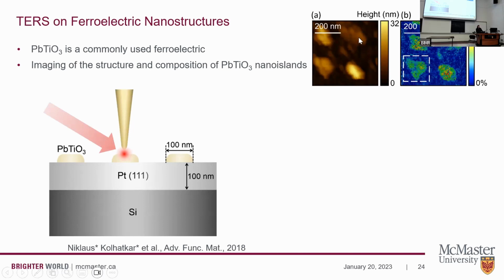So we measured simultaneously the topography, which is presented on the left, and the Raman signal, which is presented on the right. The yellow regions correspond to the lead titanate nano islands on the topography. And here we can see that we can observe the same islands, as shown in the green regions. So we got a really good correlation between the topography and the chemical image, and we're able to image these lead titanate nano islands. Now, if we look at the spatial resolution here, this is 200 nanometers. So that means that each pixel is about 10 nanometers or less.